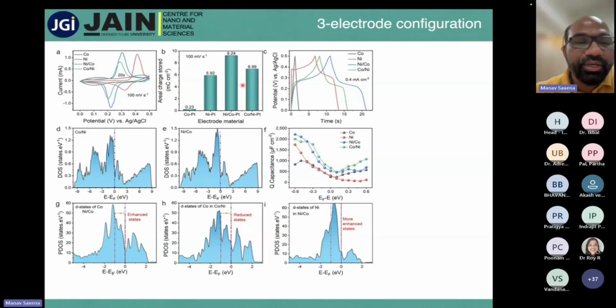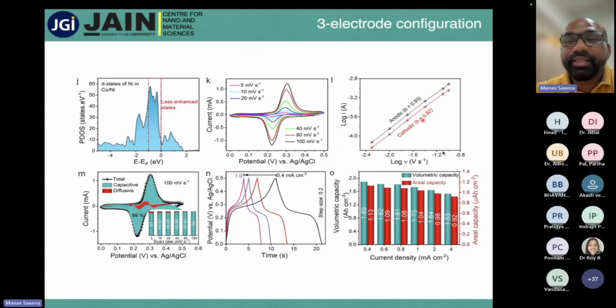So we thought, okay, let's do some theoretical study, and we collaborated and we found this for the heterostructure. There is a difference in the d states of cobalt in cobalt and nickel heterostructures, and there is an enhanced d state in the vertical heterostructures, and that is why the capacitance and the charge storage power of the nickel and cobalt heterostructure is more as compared to the cobalt and nickel, where nickel is on the bottom and cobalt on top.